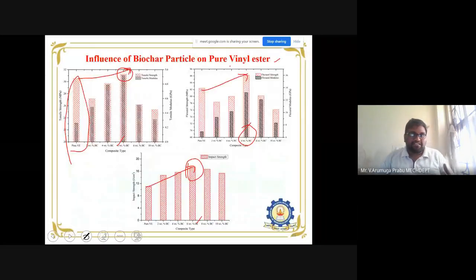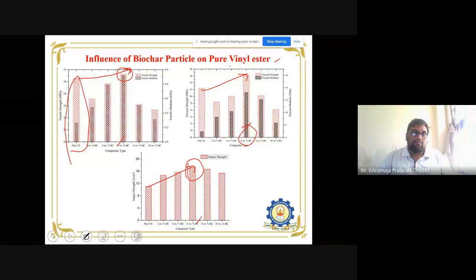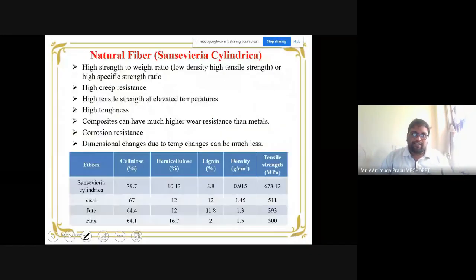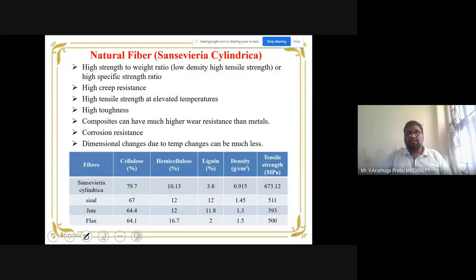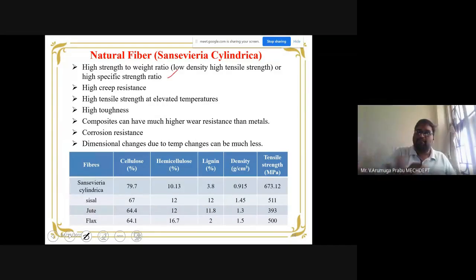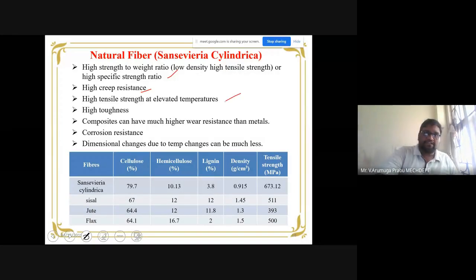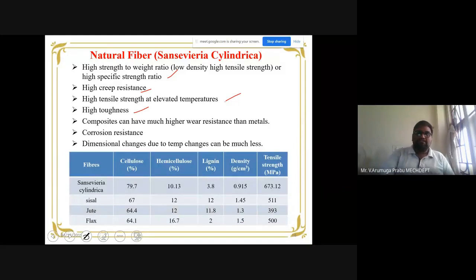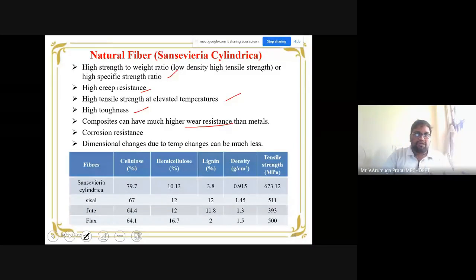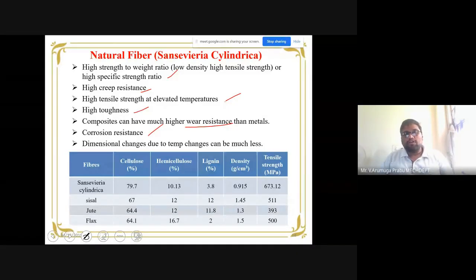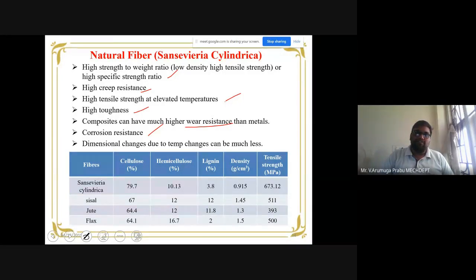Then, followed by these interesting results we obtained using vinyl ester and biochar alone, we now go for mixing the biochar with a natural fiber and see how it behaves. So here the natural fiber we have chosen is the Sansevieria cylindrica fiber, and some of the special properties of this natural fiber are mentioned here. It has a high strength to weight ratio, high creep resistance, high tensile strength, and very good toughness. It has very high wear resistance similar to metals, and good corrosion resistance. And it is not affected by temperature change, because most natural fibers are subjected to deformation with temperature change. That is not the case with Sansevieria cylindrica.